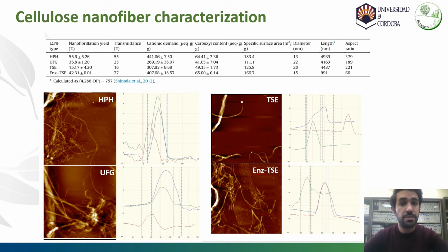If we analyze the difference between the mechanical and enzymatic pretreatment in the extruder, we see how with enzymatic pretreatment we increase the yield, we obtain a smaller diameter, but there is a decrease in the length of the fiber due to the hydrolysis produced by this pretreatment. It also affects the aspect ratio and consequently its reinforcing effect.